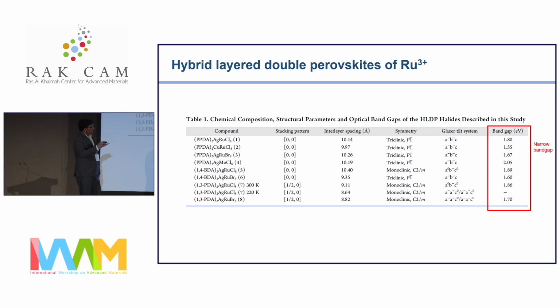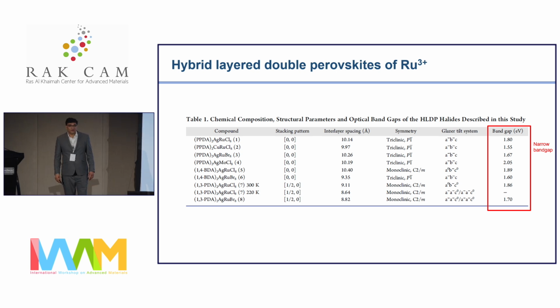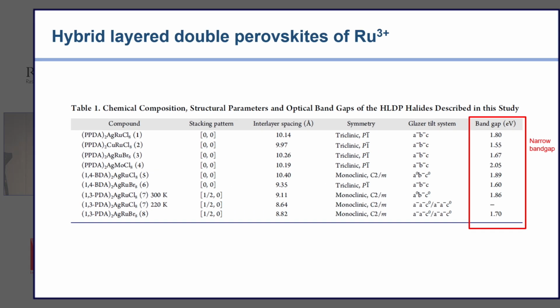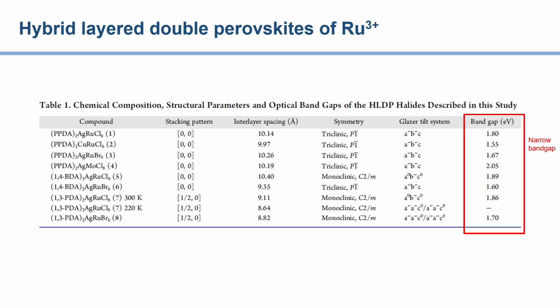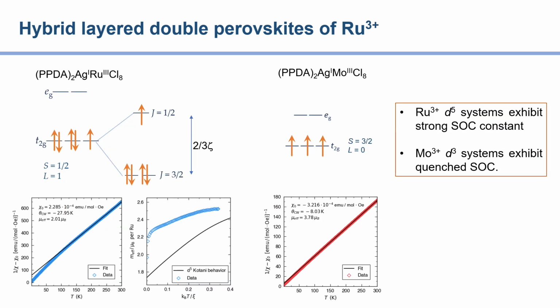You see there, band gaps are between 1.5 to 2 eV, quite narrow band gap. And they're again very stable compounds. And then we looked at their magnetic exchange interaction. So these are two types of system, as I mentioned. One is ruthenium-based, and the other one is molybdenum-based.